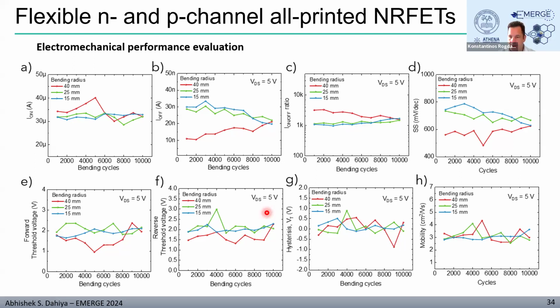Okay, thank you. Another question: which devices perform better, those based on top-down or bottom-up grown nanowires or devices? So top-down perform better. There is a reason for that. The bottom-up one I have shown is zinc oxide wires, where the bulk mobility is way lower than silicon devices, which we have fabricated through top-down. But we have also tested some bottom-up silicon, and in that case too, top-down is better.